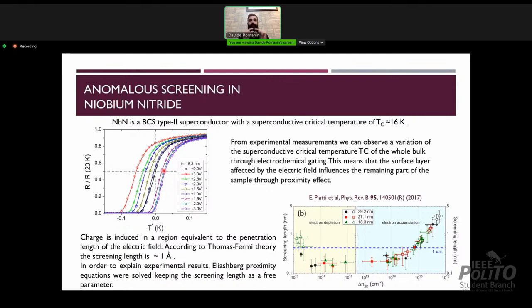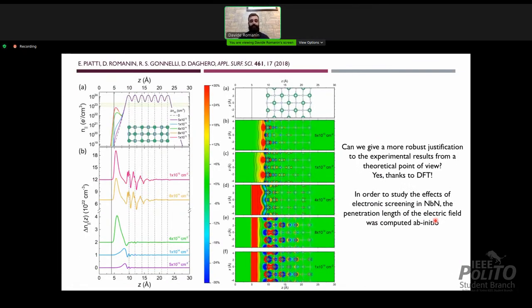Now, the penetration depth of the electric field should correspond approximately to one angstrom according to Thomas Fermi theory of screening. However, in a precedent work, they fitted the experimental results and showed that for the low doping regime, the penetration depth of the electric field satisfied the Thomas Fermi theory. However, it increases if we go to higher induced charge density, meaning that we are breaking the Thomas Fermi approximation of screening. So we have tackled this problem from a density functional point of view.